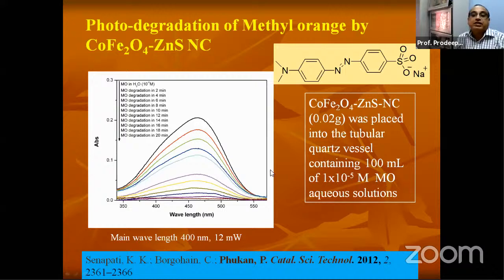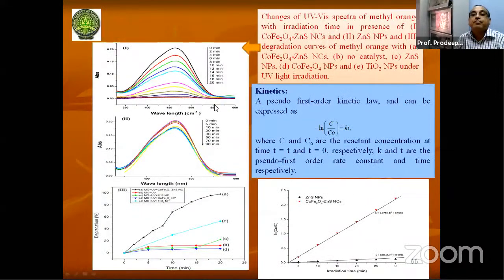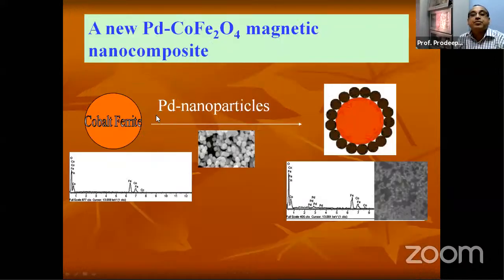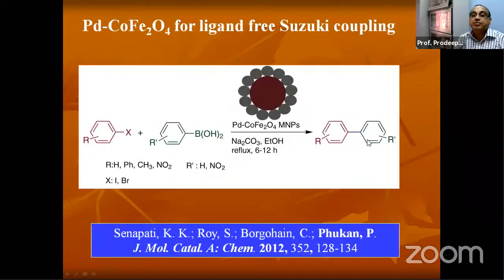So I will not talk in detail on this. It is simple and in 20 minutes it gets degraded. Already we have discussed all these things before. Then we synthesized some palladium nanoparticles. What we did, we took the cobalt ferrite, then palladium also we generated in situ and made this particular composite. And see here, then we have done Suzuki coupling reaction.